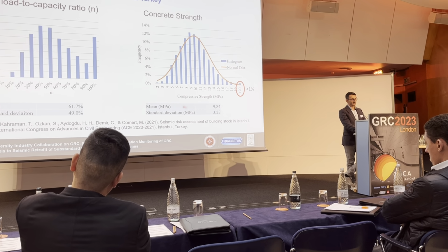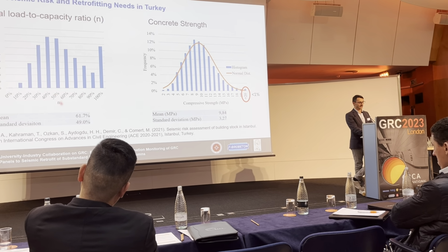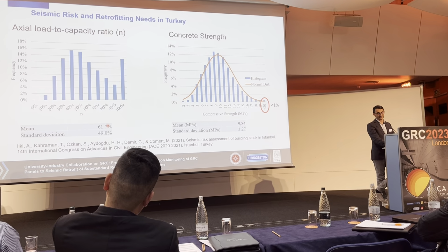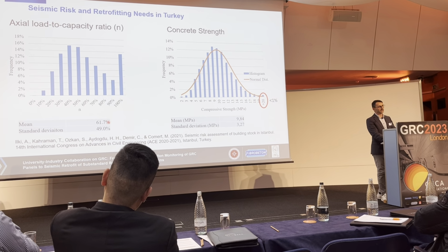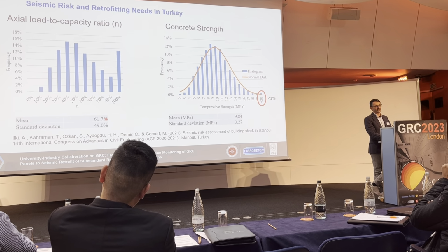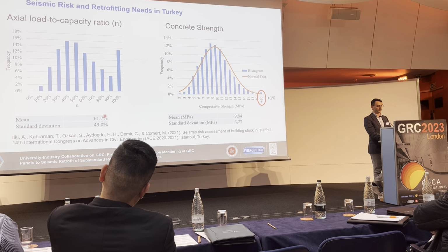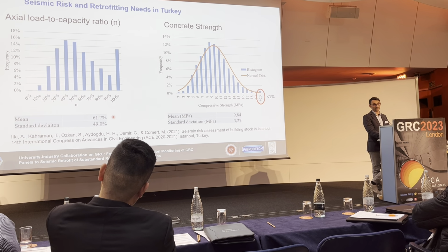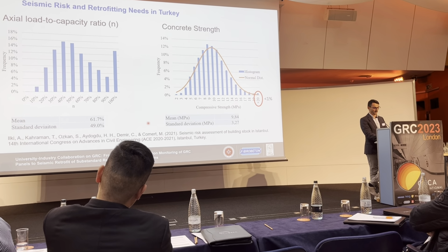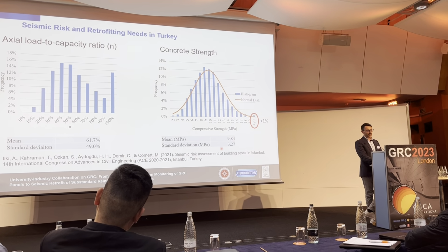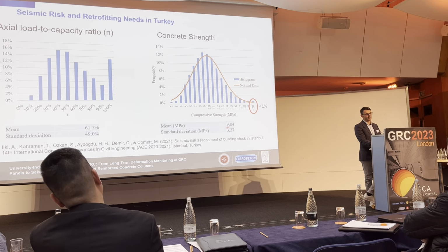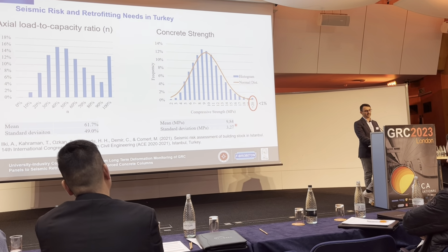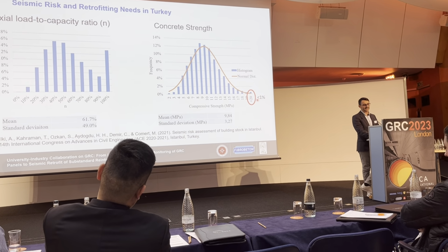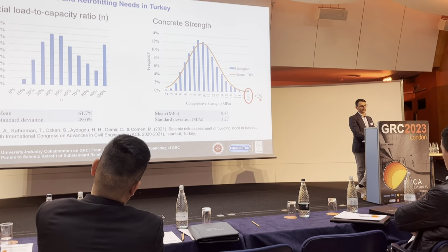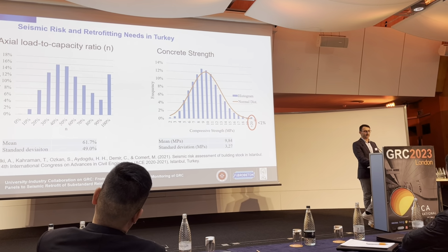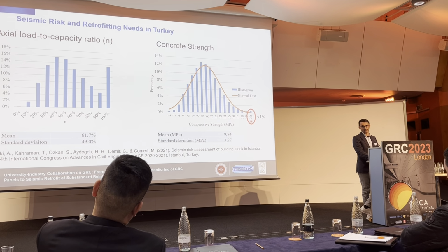Again, the axial load to capacity ratios of the existing columns, as you can see, the mean value is 60%. So it means that the reinforced concrete columns are loaded with 60% of their capacity. In seismic prone areas, it is restricted to 40% by the Turkish guideline. And the concrete strength, the mean value is around 10 megapascals, and only for less than 1% of the existing building stock do we observe compressive strength larger than 20 megapascals.